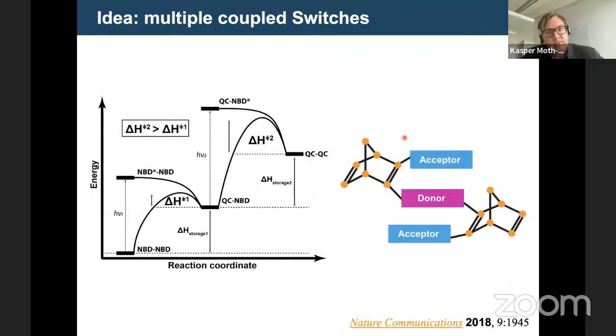The first idea was to play with the number of electrons in a box, so to say. So in this molecule, we have 2 norbornadienes and 2 acceptors and 1 donor in the middle. And if we look at the full system, the electrons can flow in the full system, meaning that we have a small HOMO-LUMO gap here, and therefore we have a small barrier. Okay, but then if we shine light on this one, it will become the quadricyclane, and then we will have another structure which is smaller. Therefore, the HOMO-LUMO gap will be higher and the barrier will be higher. So if we switch it again, we will have a bigger barrier for the second switch, and we can say that the molecule is locked in here. So if we do 2 absorptions, first 1 and then 2, then we should stay for a longer time up here. And that is a design idea.